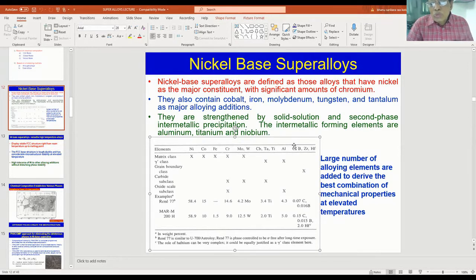Carbon combines with chromium to form chromium carbide in the grain boundaries, and it forms discrete particles of chromium carbide at the grain boundary. We require discrete particles. A continuous phase of chromium carbide is not needed for us. Boron substitutes for carbon in the carbide to certain extents. Zirconium and hafnium are grain boundary strengtheners. Now you can look at that. So many elements are there in the nickel-based superalloy, and making the superalloy is a very, very difficult task. All these alloying elements have to be controlled during the melting and subsequent processing of the material.